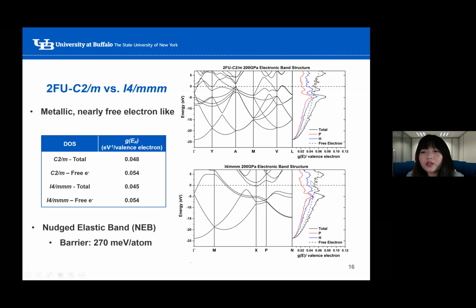For both of the structures, their density of states at the Fermi level mainly originates from phosphorus p characters and hydrogen s characters, which is indicative of hybridization. We wondered if there's a low energy pathway on the potential energy surface connecting these two structures. Therefore, we used the nudged elastic band calculation to create the pathway, and the calculated barrier was 270 meV per atom, suggesting that these two structures lie in different wells on the potential energy surface.